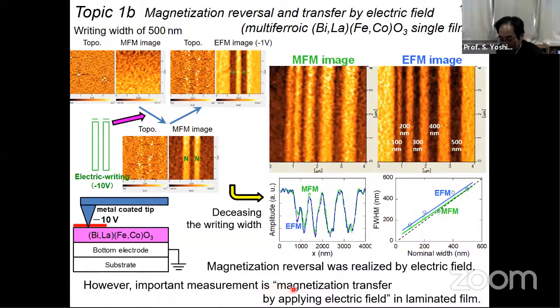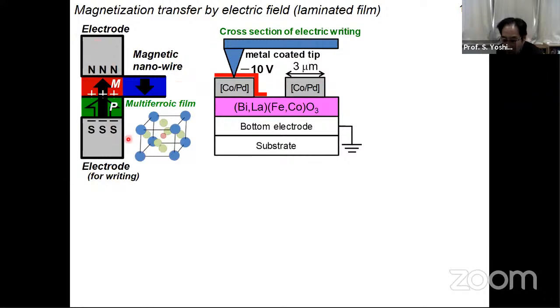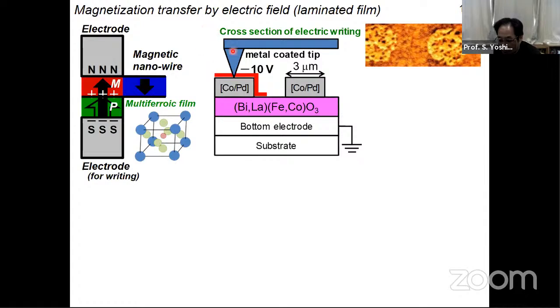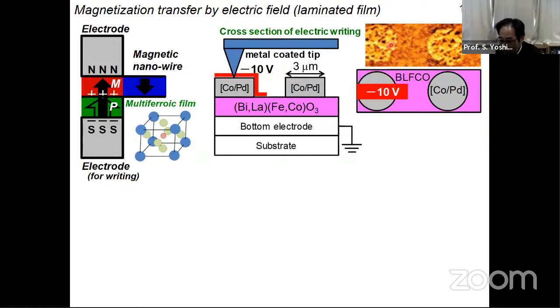However, the important measurement is magnetization transfer by applying the electric field in a laminated film. Because this one is a device image, with a magnetic nanowire here and multiferroic material here. So I fabricated a structure similar to this device: multiferroic material here and metallic magnetic material here. Before applying the voltage, this is the MFM image. You can see black parts and white parts randomly. This indicates a demagnetized structure. After that, I applied the voltage only to this dot here.